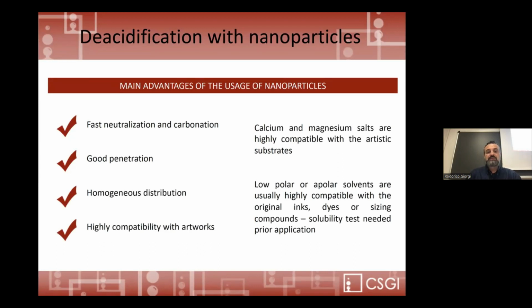And we have also high compatibility with artworks because, you know, in the whole tradition of paper making process, starting from rags, calcium salts, calcium hydroxide was used for the treatment of rags. And this means that we are confident that the presence of carbonate, calcium carbonate, but even magnesium carbonate can provide long-term durability for the artifacts. On the other hand, the use of medium polar or low polar solvents is very important because we must have some compatibility with inks, dyes, or sizing. And using nanoparticles is possible to work in a non-aqueous environment.